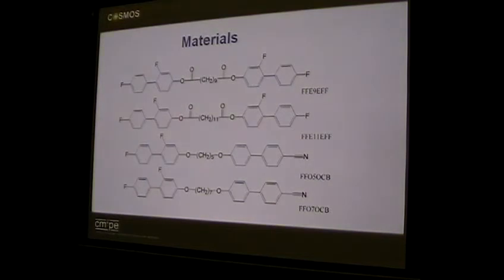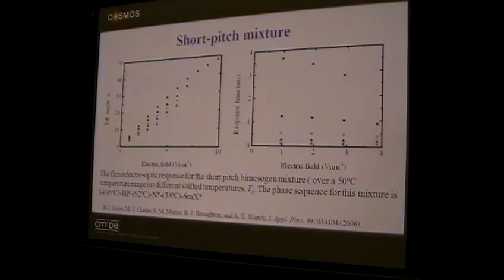What we then did was make mixtures of these compounds, because if you want to make a room temperature material, you end up making complex phase diagrams and adding sets of materials together. But note that I always used odd members, because they were the ones that give the biggest flexoelectro-optic coefficients. And then you can generate mixtures that have very large coefficients. Just to take you through some typical data, 5 volts per micron, 24-25 degrees switching angle. You have a short pitch system, a response time in this case of about a millisecond.